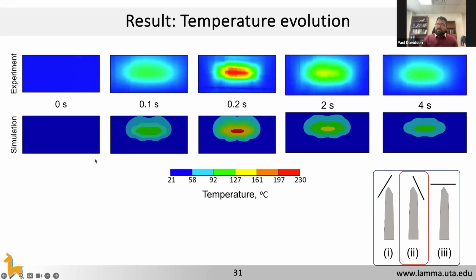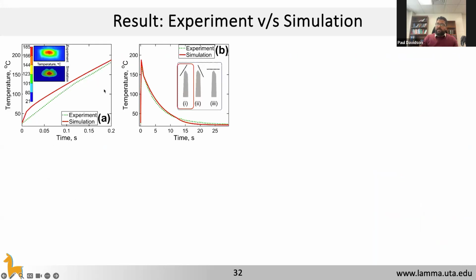Top is the experiment, and bottom is the simulation. And you can see that our temperatures match up quite well. Not only the temperatures, even the distribution, the area of coverage of the temperature matches up quite well. This is further verified by comparing experiment to simulation for different facets.